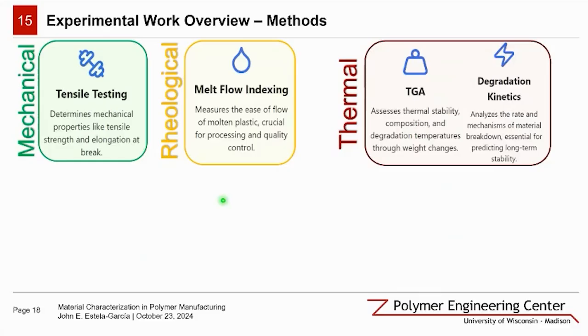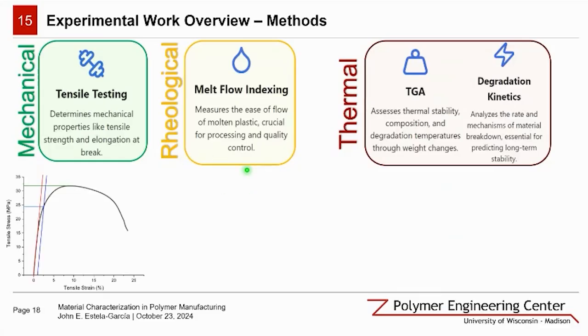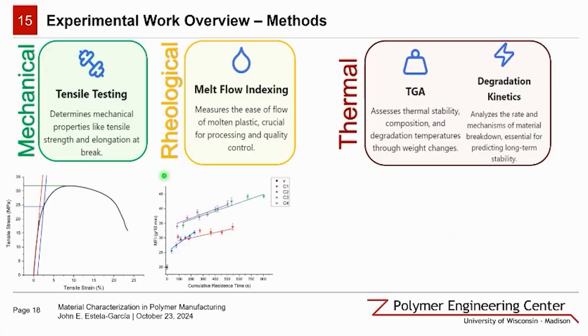We have a suite of analytical techniques to evaluate the material's property across multiple processing events. We began with mechanical testing, where we're utilizing tensile tests to determine the modulus of all samples. To ensure consistency, we injection molded samples into dog bone shapes. This approach allows us to track changes in mechanical properties as the material undergoes repeated processing. For full property analysis, we conducted melt flow index tests on pelletized samples. We then compression molded these pellets into disc for rheological characterization. And again, we maintained consistent conditions for the molding to minimize variability in our results.